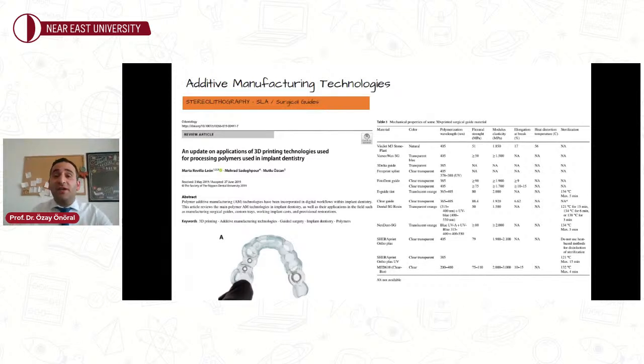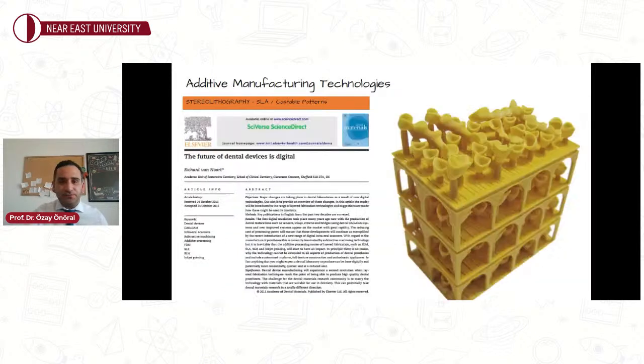For example, in the flexural strength values, 50, 80, 90, you can understand from this point of view that changing the material type will alter your mechanical, surface, or all other characteristics, although doing all the procedures with the same SLA technique and machine.